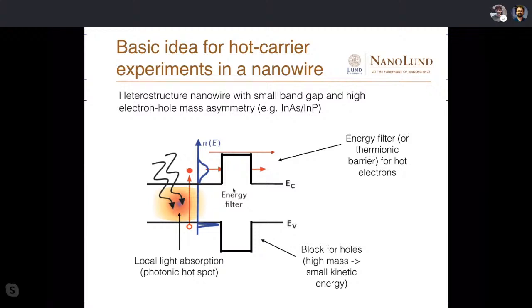You would want to have an energy filter for the reasons that I explained before. We don't worry about quantum dots here. We just go for an energy barrier, which is actually a pretty good approximation for high power and high efficiency in a one-dimensional system. And then we would want to be able to control the light absorption such that we excite electron hole pairs on one side of the energy filter, but not on the other side. Because in this case, we just ignore the holes. The holes get relatively little kinetic energy. We want them to stay behind on this side, but we want the electrons to be filtered across here so that we can separate them and then generate a thermionic voltage.